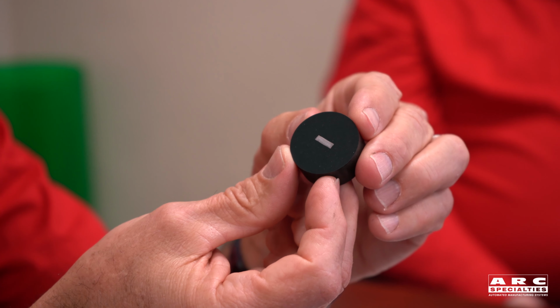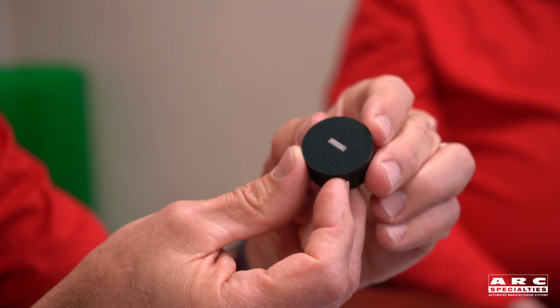When you're doing additive manufacturing, the big problem is each layer creates a certain amount of oxides, and these oxides float to the surface. And you'll typically find these in the cross sections of the weld in the form of weld defects like lack of fusion, nonmetallic inclusions. But you tested for that, right? Correct. We made a sample for destructive testing. We then cross-sectioned it, mounted it, polished it, and etched it, so that we could micro-examine the grain structure for discontinuities, lack of fusion, porosity, non-metallic inclusions, and we found none of that.